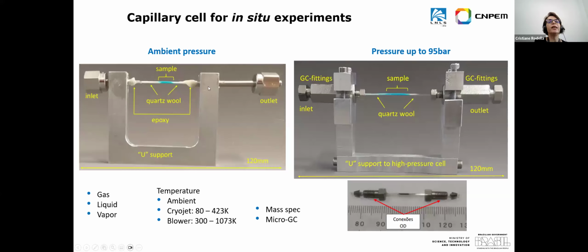This example of the cell, we put to work at ambient pressure, because we glue the capillary to the cell at these 2 points, and we seal the cell. But when pressure is required in the experiment, the glue won't hold the pressure, so we have a more sophisticated system. It's a very similar cell reactor, but what changes especially is the way that we seal the capillary cell to support pressure. And here's the system inside that we have to install to keep the pressure during the experiment. I can tell you it's a much more sophisticated system to prepare the sample, to keep the sample here, and increase temperature and increase pressure.